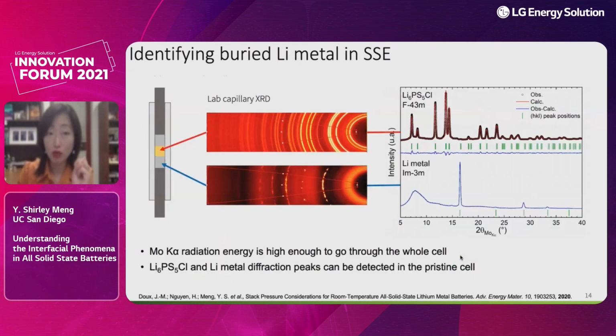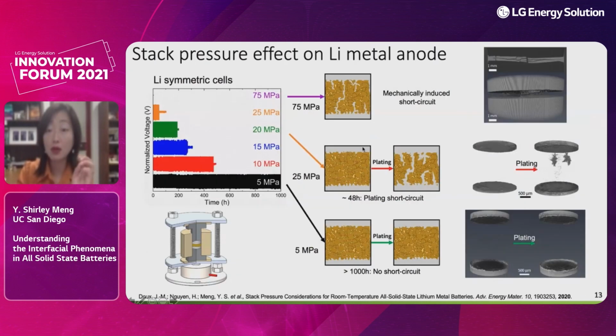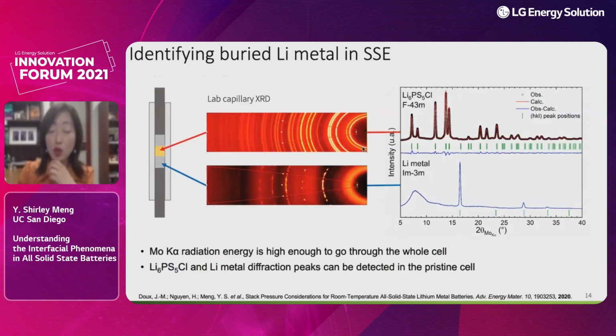However, we still have another problem, which is the critical current density. Even though we lower the pressure, we still have this problem because the cycle numbers I showed always involve a very, very low critical current density. So let's spend some time to understand what happened for the critical current density. Did we really produce lithium metal, or did we produce something else? The CT only shows you the morphology, but doesn't tell you the chemical species.